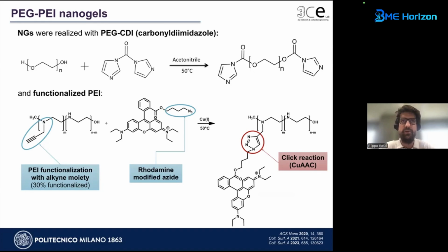In this case, as you know, the main difference is that while polymeric micelles form nanoparticles through self-assembly, so it's something physical, there's no chemical reaction. In nanogels, there's a chemical reaction between bonds. So we started with PEG, polyethylene glycol, with carbonyldiimidazole, with functionalization.